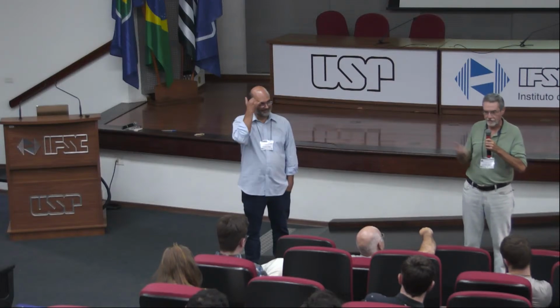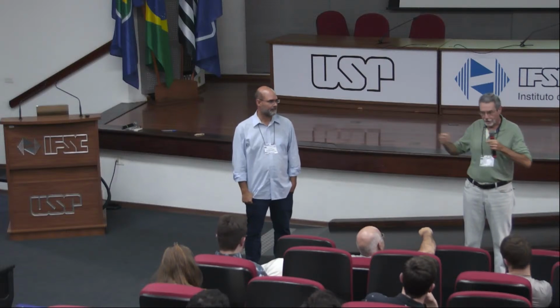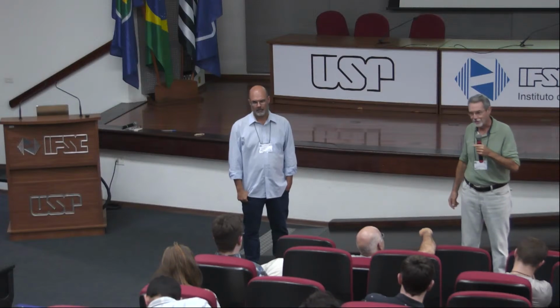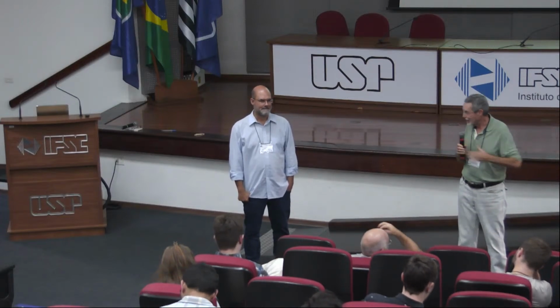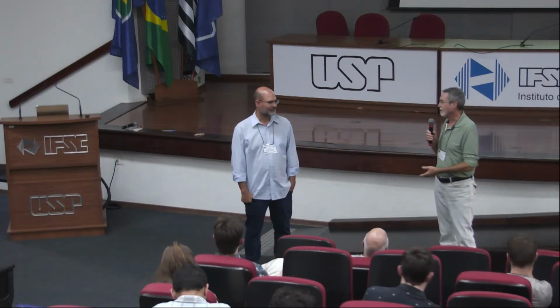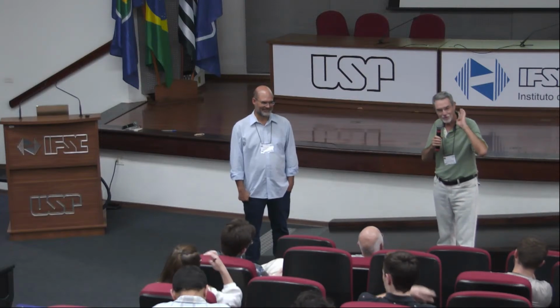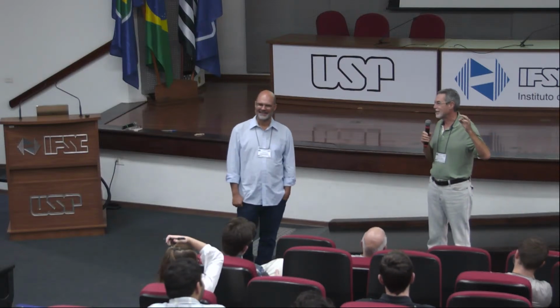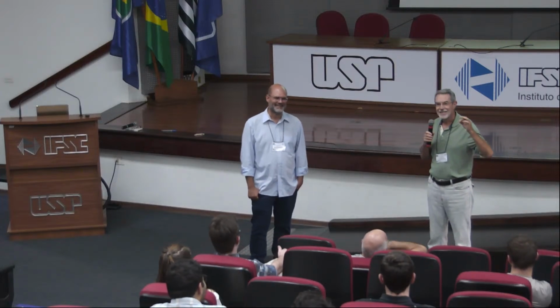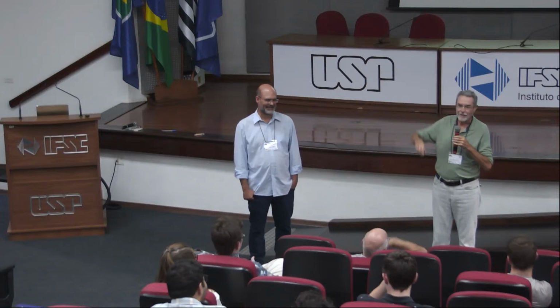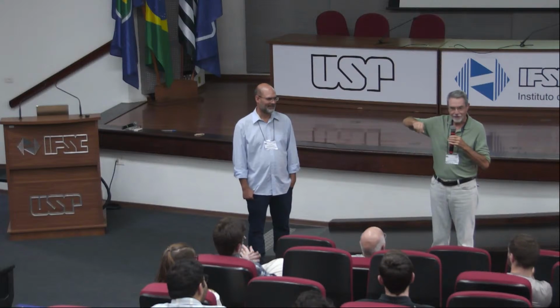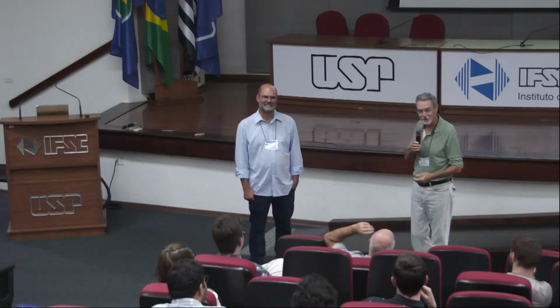And he wanted to measure crystal growth rates. So he said, okay, Bill Doyle is this guy. Bill, you make a long bar-shaped sample. You build your gradient furnace. In the old days, you had to build your equipment. And he left this glass inside for 4 years. He was doing some other things, of course, doing his PhD. After 4 years, he took the glass out, and nothing happened. Then he discovered that he had to spray a powder of crystalline albite, mineral albite, to trigger nucleation. And then he had crystal growth, and he measured crystal growth. So 4 years is good. It's a good human time scale for a PhD work.